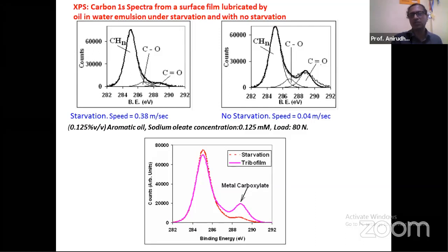So because of this chemical reaction between iron, the hydrocarbon, and this water, under suitable conditions, these metal carboxylates are formed because of tribochemical reactions, and the structure of those metal carboxylates is similar to that of grease. They are greasy compounds. They are highly lubricious, soft compounds which would allow easy slip or cleavage or shear, providing a very lubricious film. So this is from our XPS data.